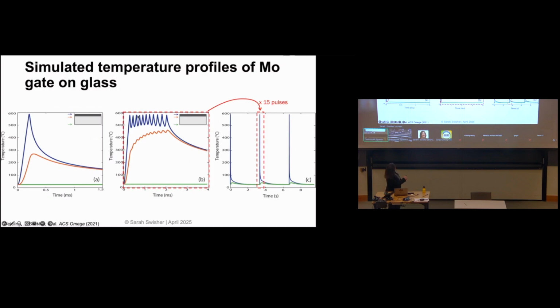So one of the great things about the tool that we have is we can design what we call micro pulses. So this is actually the lamp turning on and off, on, off, with about 1 microsecond resolution. And by doing that, we can create these thermal dwell time, basically, where we stay at about 500 degrees for 2 milliseconds. So this would be 1 pulse, and then we can repeat that. Here I'm showing all of this contains this whole pulse, and we can do that multiple times.